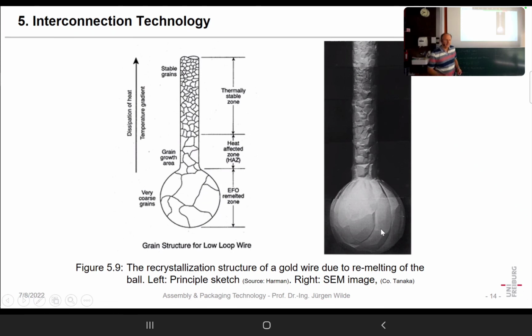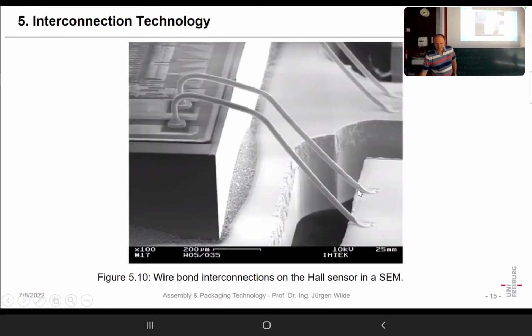Here they did, I think they used a so-called focused ion beam. So you shoot gallium ions on the surface, and the etch rate of grain boundaries is higher than the etch rate of a grain. And in that way, we can see the grain boundaries. And as we know, every one of these grains is a single crystal of gold.